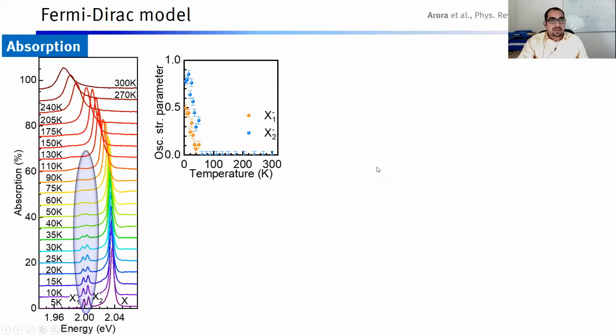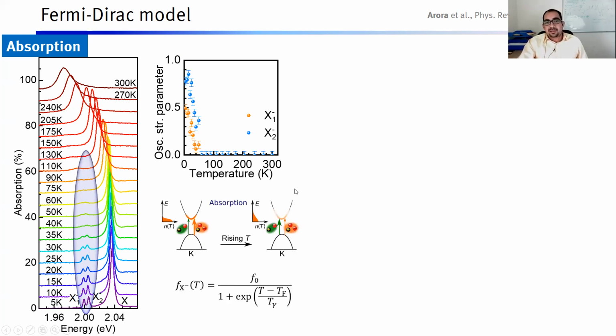Let's see the oscillator strength. Essentially, we have to measure the absorption spectrum. We have to look again at this region of trions. We are raising the temperature and we see that the oscillator strength falls for both of these trions for the reasons which we had discussed earlier. We had discussed this, so I will not go into this again.